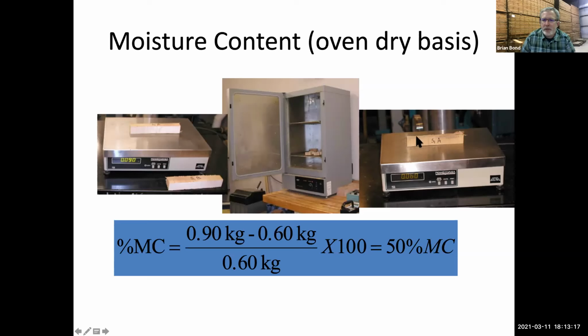Well, you take that piece out, you weigh it, put it back in the oven for a couple hours, come back and weigh it again. And if it's losing weight, that means you still got some moisture to lose. You still got some drying time you got to do. If it's the same weight, hey, you're dry, you're oven dry, you're good to go. Go ahead and use that value in your calculation.